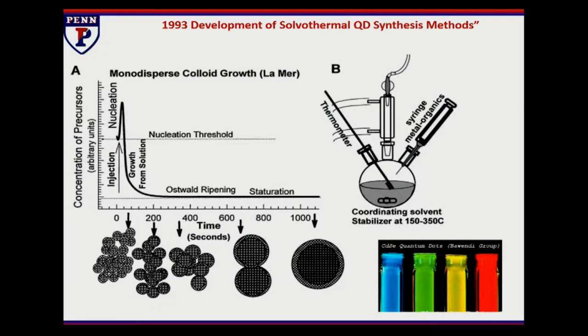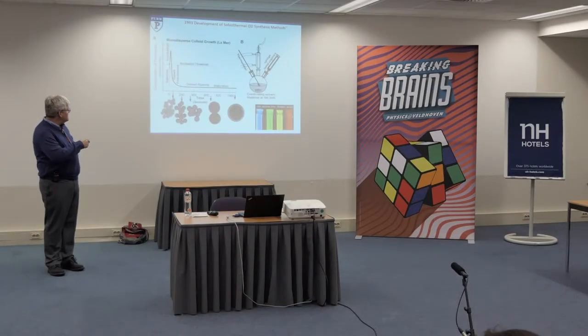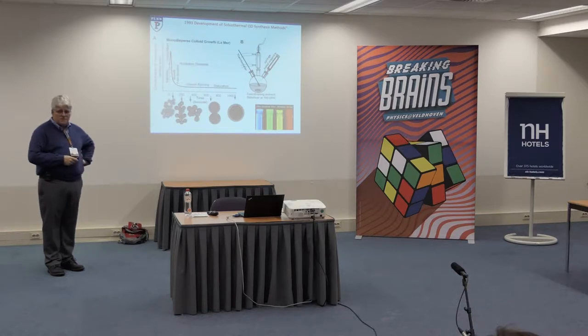So this is a process of controlled nucleation and growth that we take advantage of for most of the systems that I'll discuss today. There is generally an initial growth phase that is triggered either by a ramp in temperature or a spike in the concentration in the solution, and that's followed by a period of growth that occurs below the nucleation threshold for new particles within that solution, and that's really important.